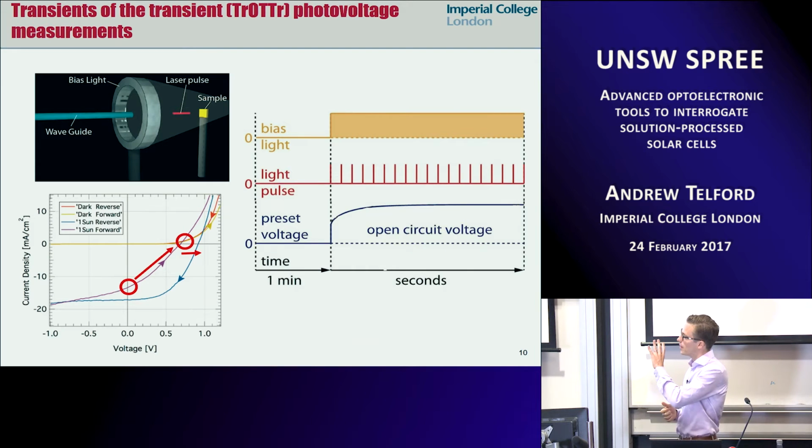And the way we came up to understand it is by tweaking with transient photovoltage spectroscopy, in order to be able to look at this problem from two different timescales. So you have your slow evolution of the voltage after preconditioning in the dark at short circuit, which is this blue curve here, and that can last up to a minute, so that would be your slow transient. And then on top of that, every second we will use a pulsed laser to collect a snapshot of the electrostatic potential, if you want. And that is by simply looking at the transient photovoltage.